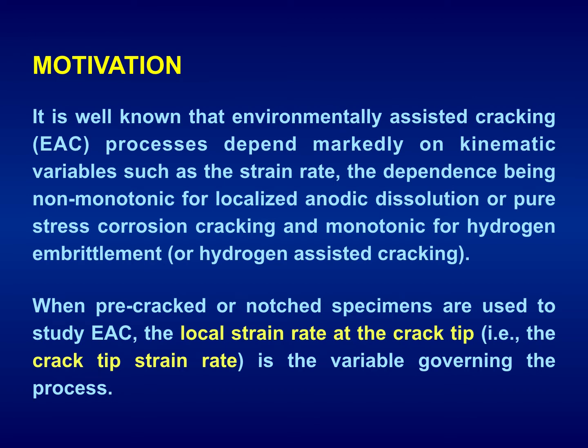It is well known that environmental assisted cracking, EAC, or in traditional terms, stress corrosion cracking, SCC processes, depend markedly on kinematic variables such as the strain rate. The dependence is non-monotonic for localized anodic dissolution or pure stress corrosion cracking, and monotonic for hydrogen embrittlement or hydrogen-assisted cracking. When pre-cracked or notched specimens are used to study environmental assisted cracking, the local strain rate at the crack tip, the crack tip strain rate, is the variable governing the process. It is the local strain rate just at the crack tip or in its vicinity, the so-called crack tip strain rate.